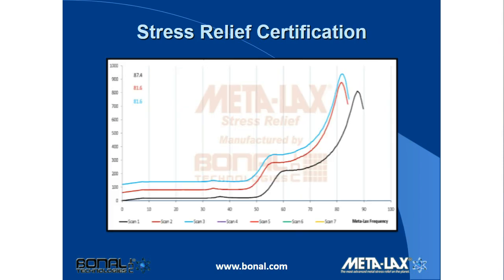This certification sheet shows a job one of our customers Metalax stress relieved. The initial harmonic peak was at about 88. Vibration was applied in the subharmonic zone down around 73. The second peak shifted to 82, indicating stress relief occurred. Vibration was applied for a second time period at about 70. The third scan repeated in the same place as the second — around 82 — indicating stress relief is complete. There is no size or weight limitation for parts that can be treated. Larger parts are processed in 15-foot sections at a time, and you will get a certification sheet for each location treated.